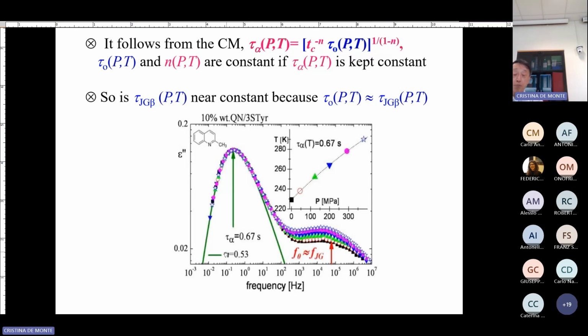What they have done is many different pressure and temperature. See this track here, pressure, temperature, and you see that they are again the same. The alpha remains the same shape, and the so-called JG remains in the same place. Now the relaxation strength is not the same, but you can see that they remain the same. And you calculate the coupling model using the equation here, you get nearly the same peak position as the experimental relaxation time.